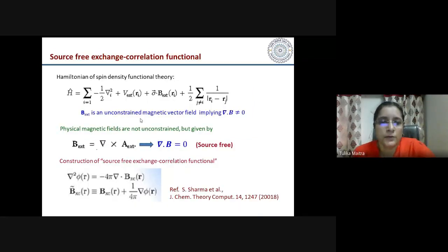So to resolve this, we recently performed calculations using a newly developed exchange correlation functional, which is known as the source-free exchange correlation functional. What is done here is that the spin density functional theory Hamiltonian, which is given here, can be written like this, where the potential can be divided into 2 parts. One is the spinless part, and the other, the spin part, can be written in terms of a magnetic field. But this magnetic field is not a constant magnetic field, so it can have a finite divergence, whereas physical magnetic fields cannot.